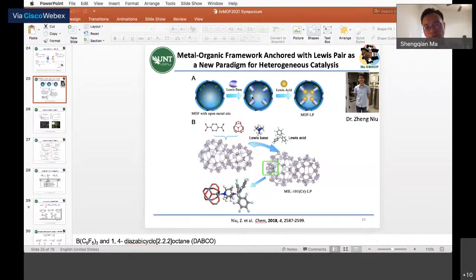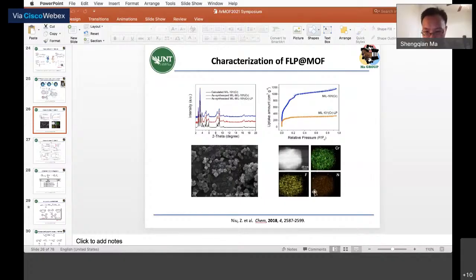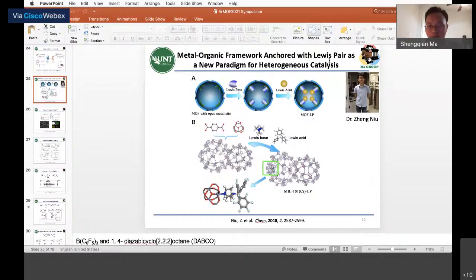We don't put in all the open metal sites under control. Each Lewis pair corresponds to one Lewis acid, and we also control the loading of the open metal sites. I think the current loading is less than 50%, and you can see the uniformness in those EDS. They're very uniform inside the pore. Also, we have the fluorine mapping. It's not accumulated at a certain area. It's uniformly distributed in the MOF, because this is not really loading. It's more like an anchor.